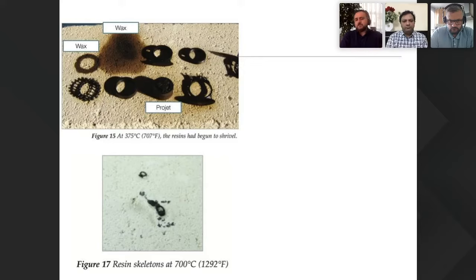And we push up to 700 degrees, which is quite a high temperature. You can see that those resins have ash remaining—some of them may have more ash, some may have less ash, okay?